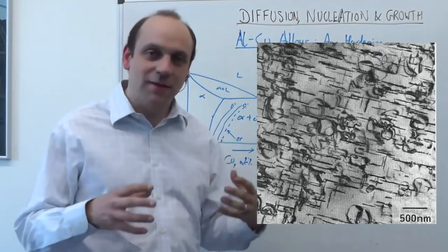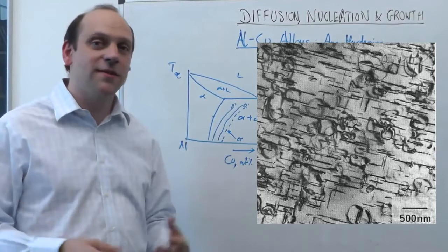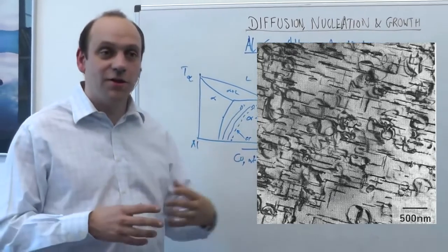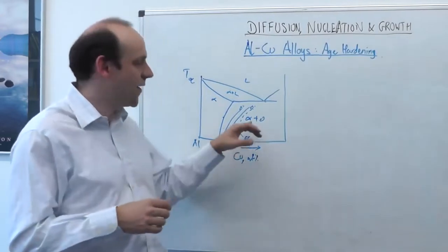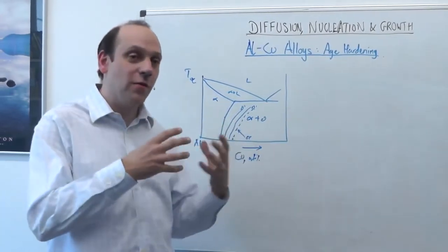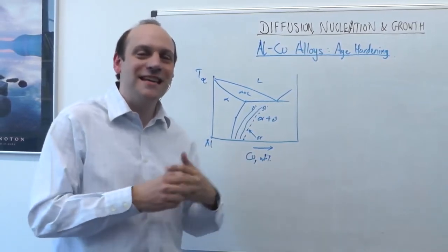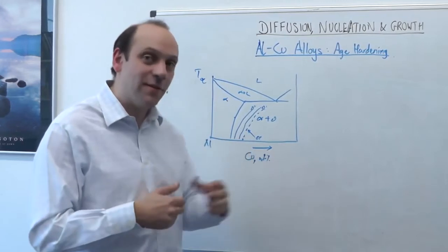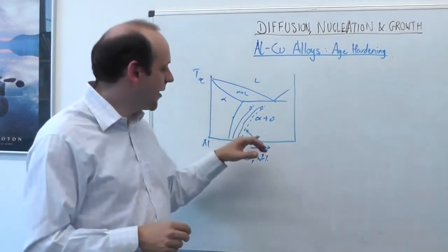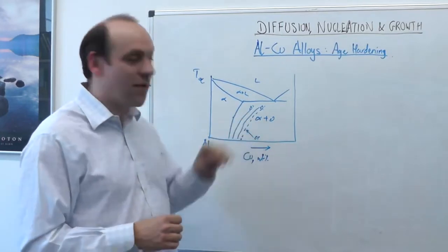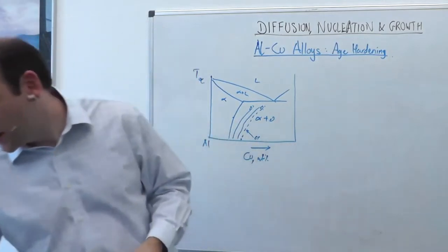And so that's a way in which aluminium can nucleate the final theta phase with a big surface energy that requires quite large nuclei. And how did it get the nuclei? Well, first it forms some metastable phase, some phase that's not in the equilibrium phase diagram, but is something that forms during the transformation sequence that's easier to form, that doesn't have as much surface energy. So it's so-called metastable. And that would be the GP zone, and then the theta prime, and then the theta double prime, a sequence of phases, which we'll study in third year in 307.